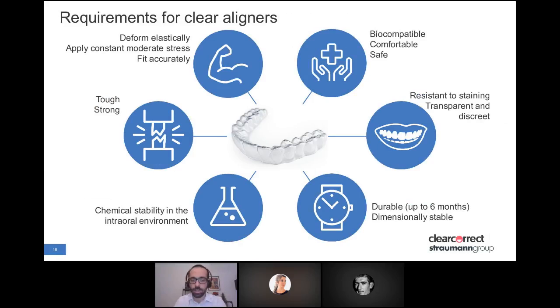When it comes to specific requirements for the clear aligners, one requirement is that they should ideally deform only elastically. They shouldn't deform permanently, especially when they are inserted or removed from the mouth. They should apply a constant moderate force or stress, and they have to fit accurately in the mouth. They also have to be tough and strong, chemically stable in the intraoral environment, biocompatible, comfortable and safe. They have to be durable, normally for a couple of weeks, but in some cases up to 6 months, especially for the last aligner. For aesthetics, they have to be resistant to staining from foodstuff like coffee, which is a highly staining agent, or mustard also. And they have to be transparent and discreet and not visible at talking distance.